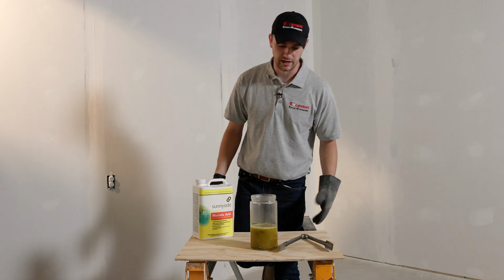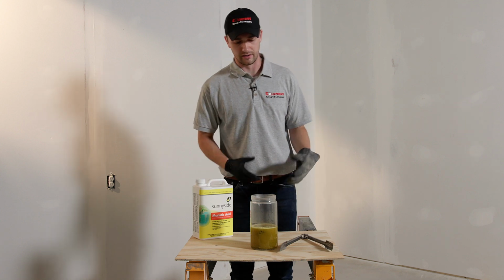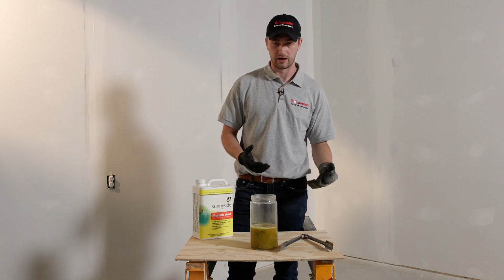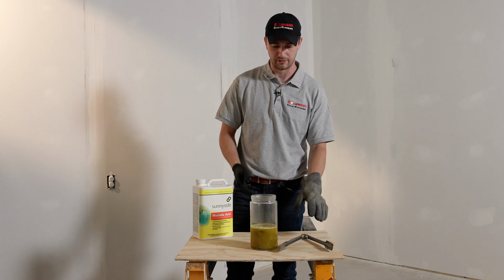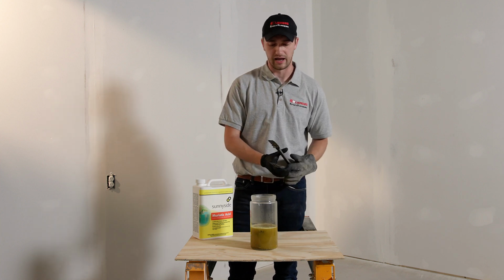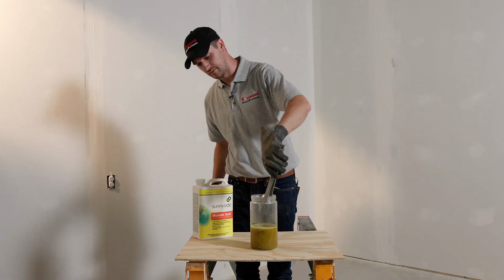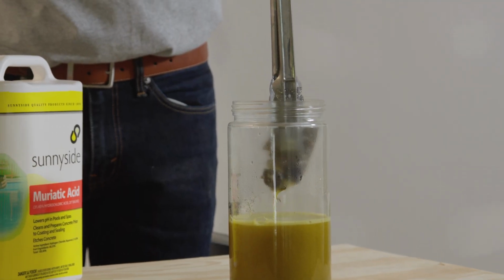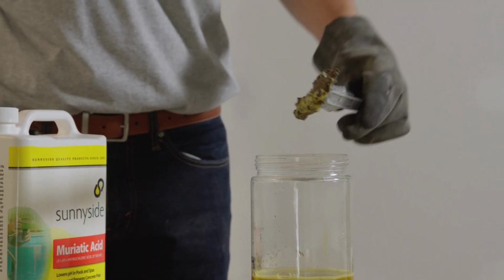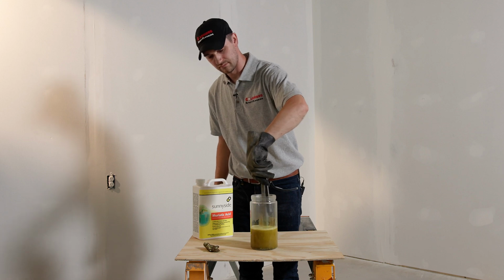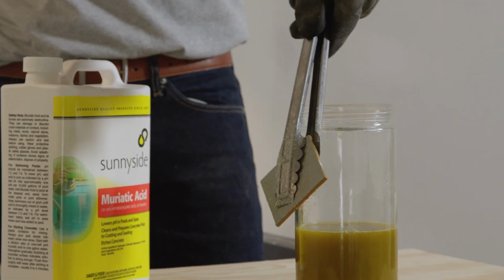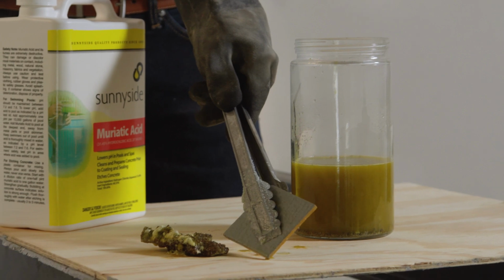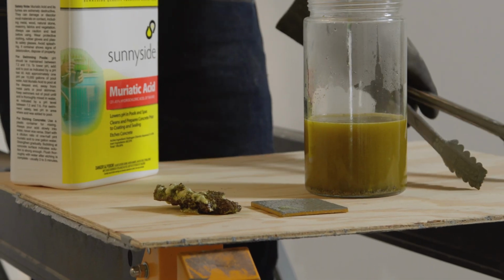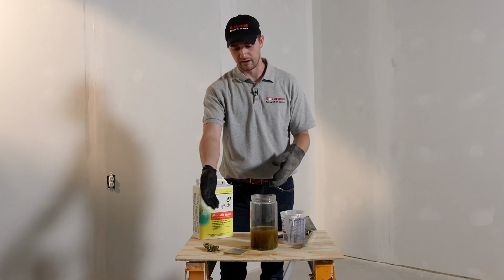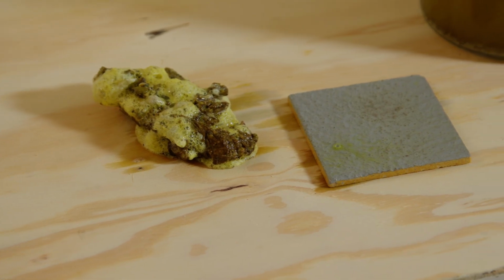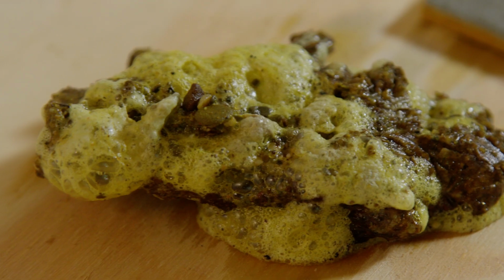All right, so we've let about 10 minutes lapse here. And we're gonna pull out both samples of the concrete and the urethane cement to see how they've held up to the muriatic acid. You can definitely see a chemical reaction within the jar here. So you can see here between the concrete and the urethane cement sample how well the urethane cement has held up compared to just a bare concrete.